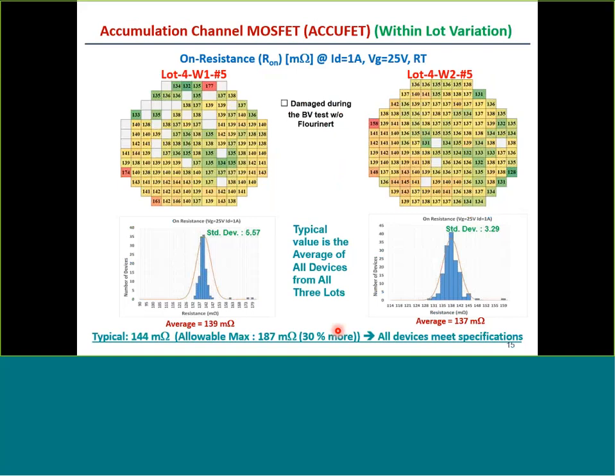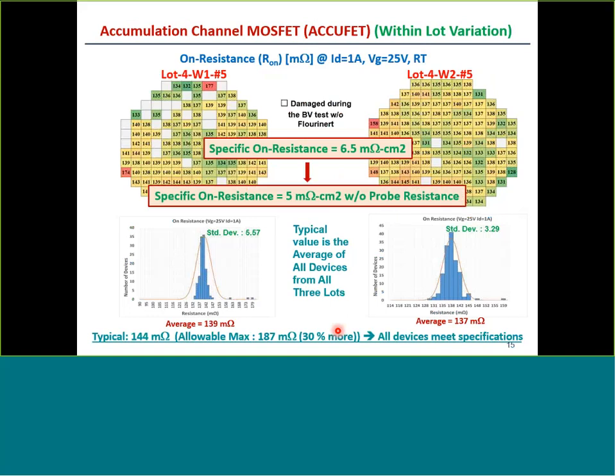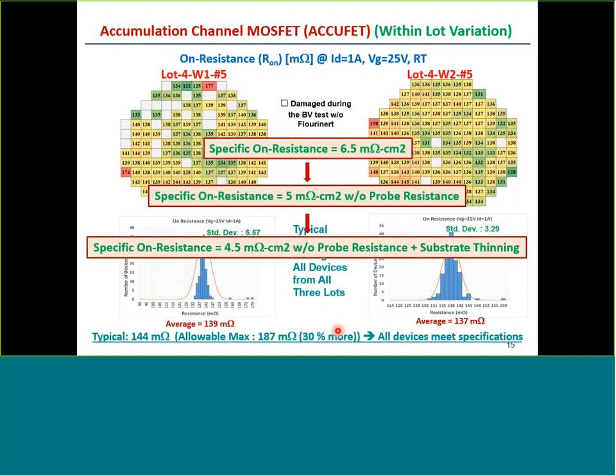So what the data shows here is that the average value for all the wafers in all the lots is 144. So for these particular wafers, you can see the numbers on the chart, and the distribution is also very tight. So I want to convert these numbers into a specific resistance because many of you like to know that. So using the active area from the previous chart, it works out to be 6.5 milliohm centimeters squared. If you take away the probe resistance, then this would be 5 milliohm centimeters squared. If you proceed to thin the substrate, then it is possible to bring this down to about 4.5 milliohm centimeters squared.